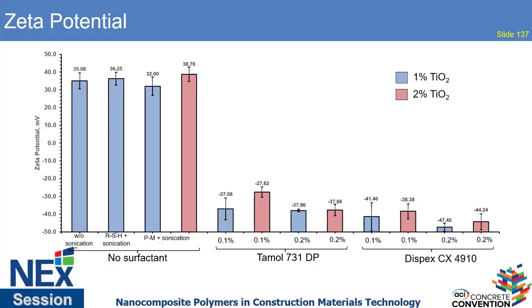We need to look at multiple things. One other reason why we were using different surfactants was that we were trying to achieve different pHs. As you're working with coatings or cementitious materials and trying to incorporate those nanoparticles, you don't want to hurt the system. You want to make sure that your nanoparticles are stable, but you also need to make sure that the systems where you're incorporating those nanoparticles are not affected by the interactions. For example, if you incorporate titanium dioxide in a coating, since the specific grade we are using decomposes organic matter, you will have to incorporate it into something that has inorganic content, something like a silicone coating. And in this case, you need to ensure that the stability of the silicone emulsion will not be jeopardized by the nanoparticles incorporated in it.